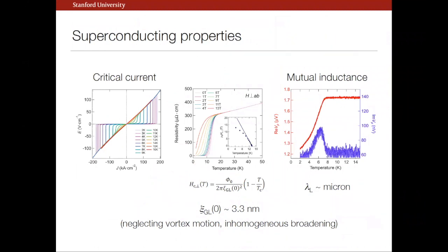So to give you the basic superconducting properties, the critical current here, let's say the narrow bridge of this guy is at that point pushing 200 kiloamps per centimeter squared. I should say now we're up to 350 or 400. And so it's indirect, but one of the ways that we felt convinced it has to be attributed to the uniform film rather than an interface is this would require many orders of magnitude higher critical current density than, say, seen in 2D systems like TMDs or bilayer graphene or interface versions of this.